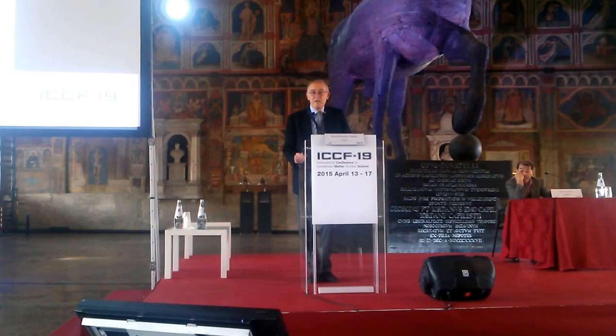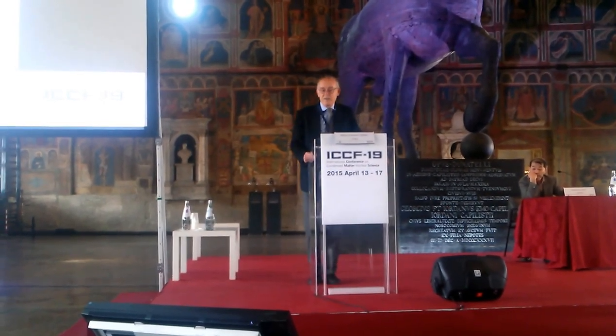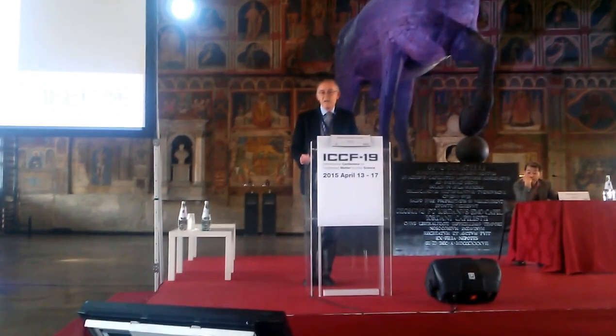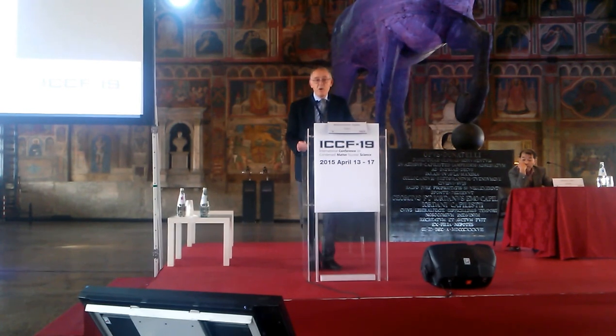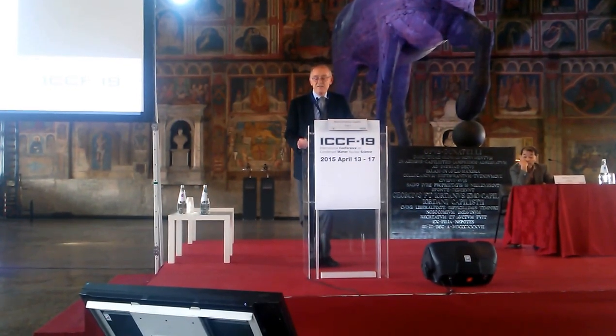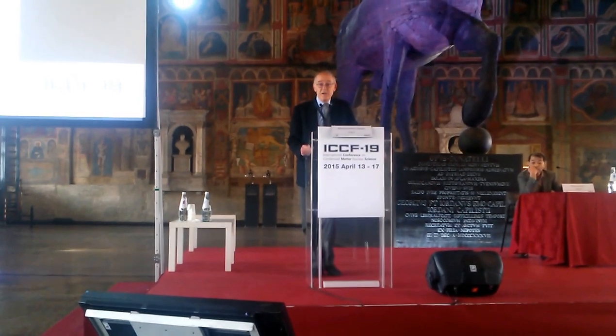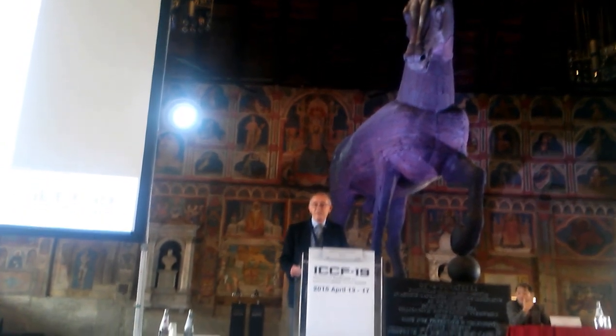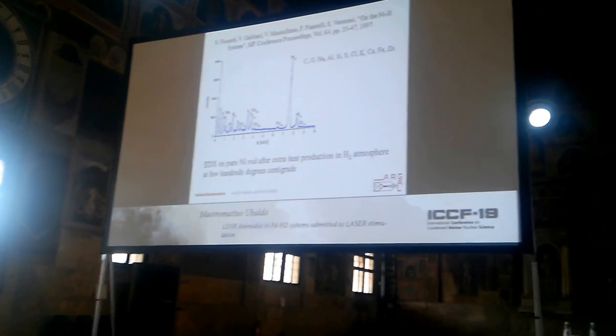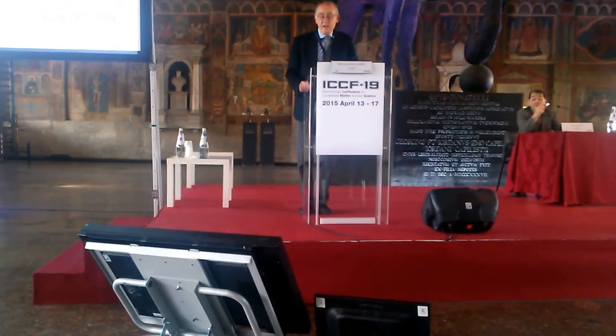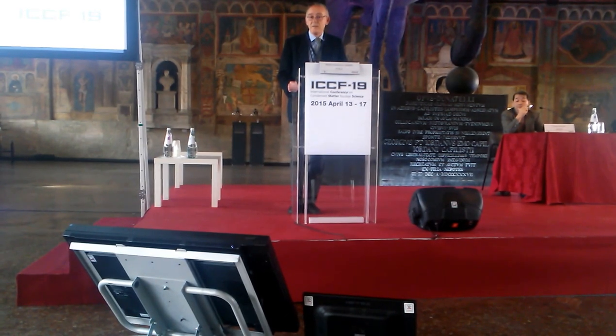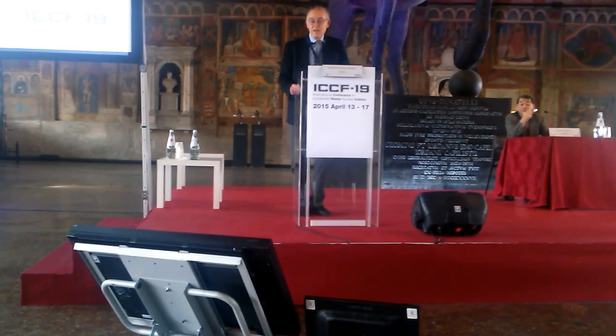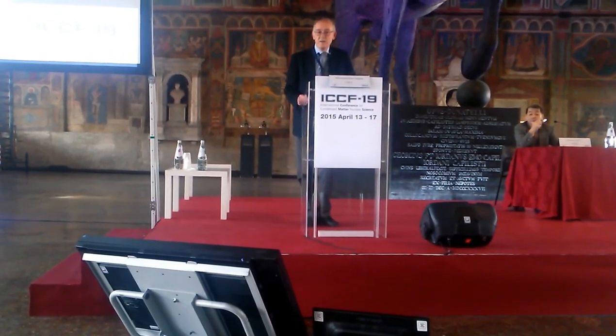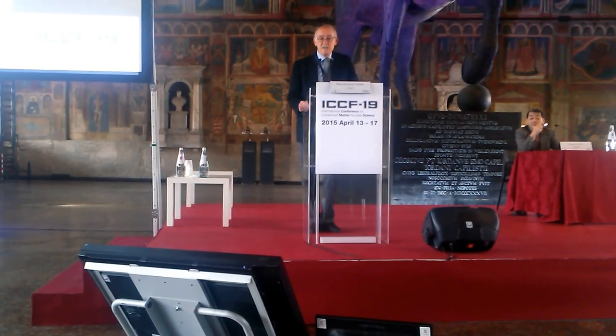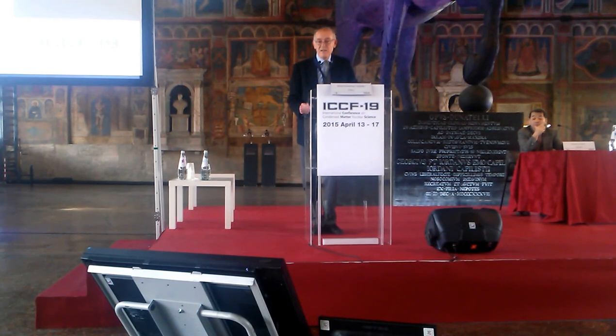First important background findings are from Piantelli and others in the Siena lab, working with nickel rods and hydrogen at a few hundreds of degrees. The temperature was about 350, 400 degrees. And after some experiments giving a very big excess heat, they analyzed the region of the material where they observed some reaction. And they got EDX analysis of the material in several zones.